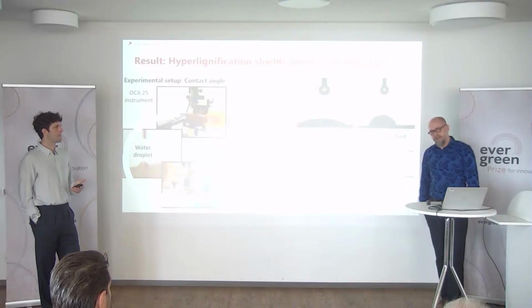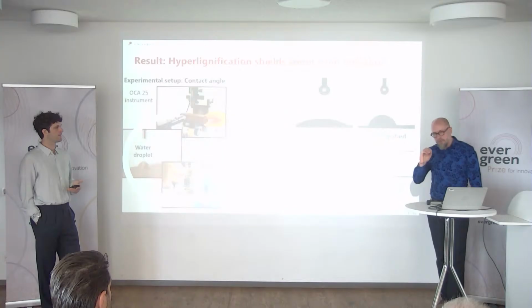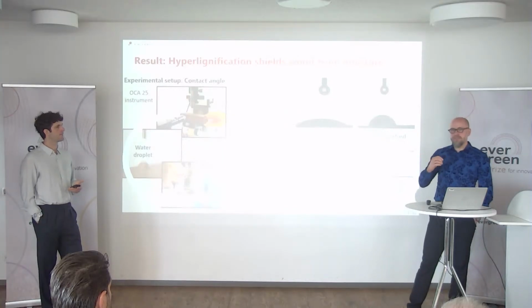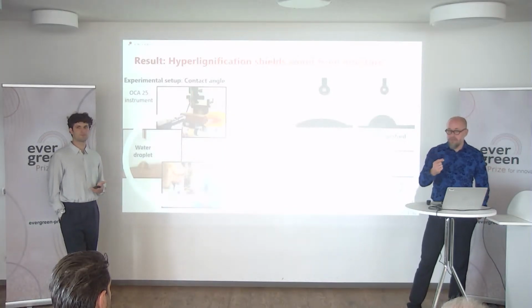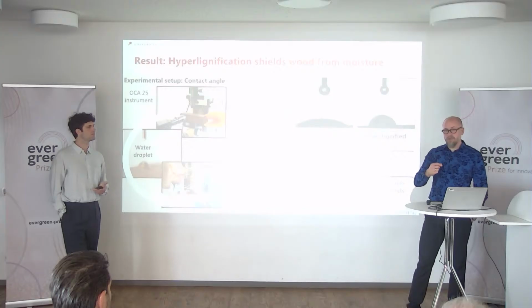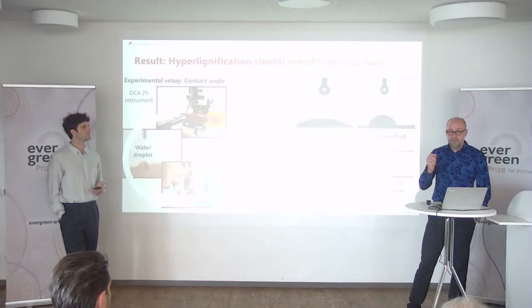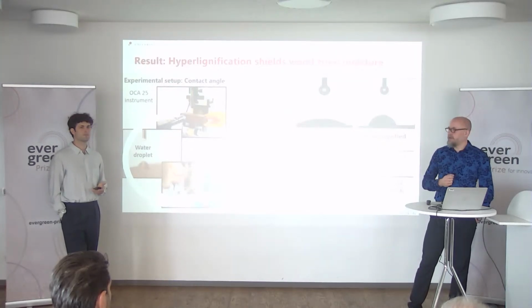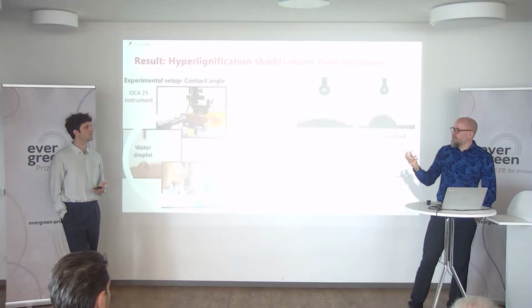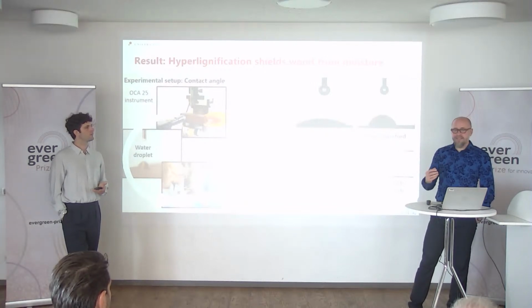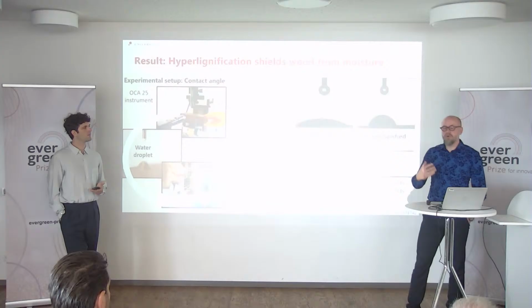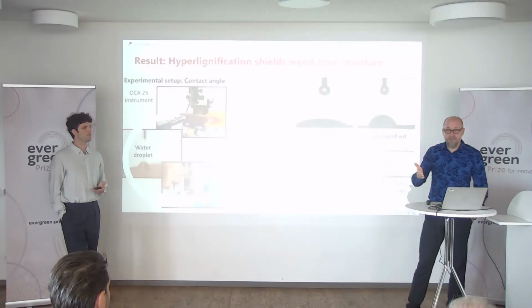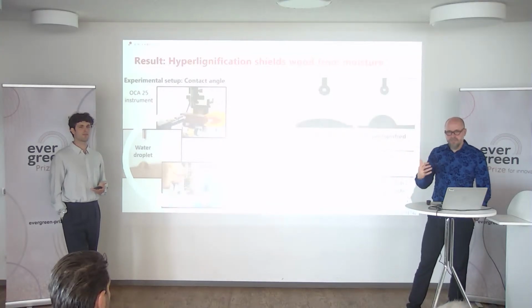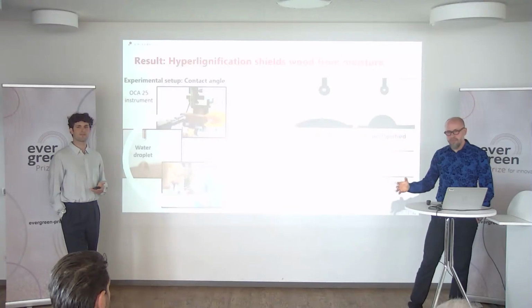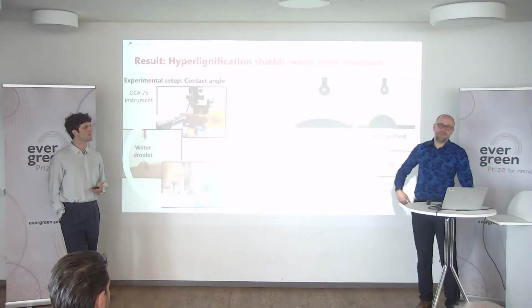It's in the planning. But what we expect is that since some of these molecules penetrate the cell wall, we have this bulking effect of the cell wall, meaning that there's less space for water, so we expect it to swell less, to be more dimensionally stable. And that's also a reason why we expect it to be very durable: the wood is more dry, a bit like other modified wood, where you exclude water from the cell wall and hereby create a more stable material that's also less attractive for fungi.